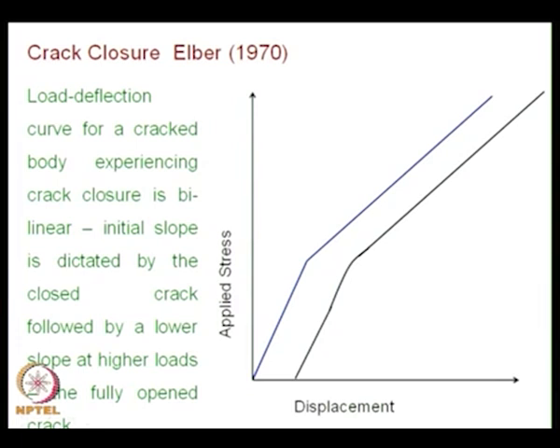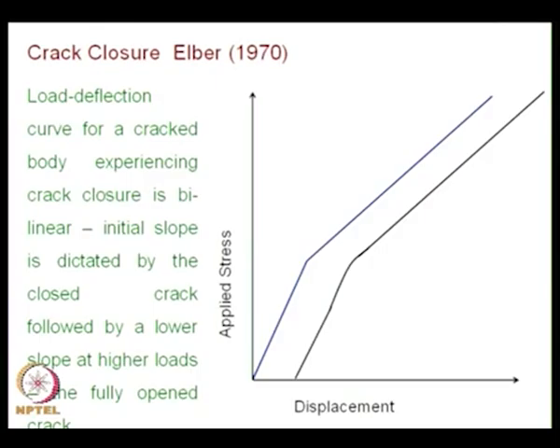And the question here is, how will you identify when the crack closes and when the crack opens? This is a very difficult thing to measure experimentally, and people have found various ways to do that. One way of describing this is, you say at this stress, when there is a transition of the slope, the crack is fully opened, and when the curved portion becomes straight here, you say that the crack is closed, or part of the crack is closed. So, this is one way of estimation. At this stage it is also wise to look at what was the history in the case of crack closure.